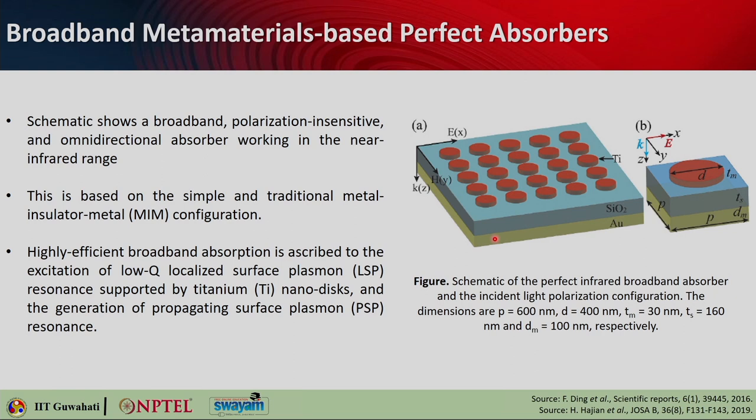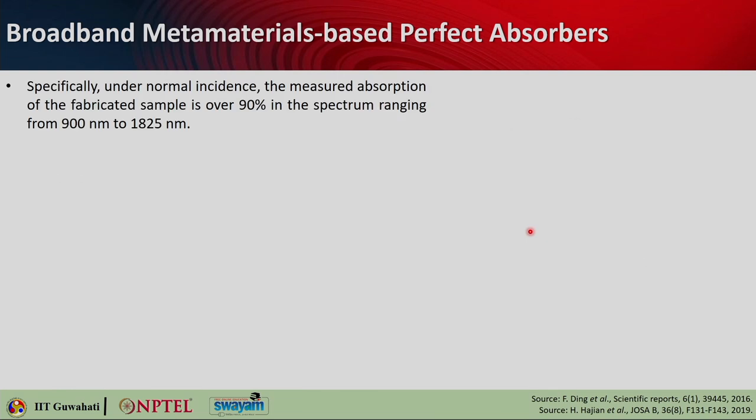So, here what happens, the highly efficient absorption is mainly coming from the excitation of low Q localized surface plasmon resonance, which are supported by the titanium nanodisks, and you are also generating the propagating surface plasmon resonance in the interface between the gold film and silica.